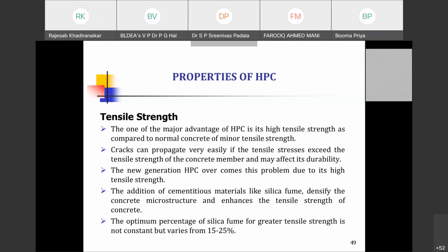The addition of supplementary cementitious materials, or SCMs, like silica fume or fly ash, densifies the concrete microstructure and enhances the tensile strength of the concrete. The optimum percentage of silica fume, as you have seen earlier, is around 15%. They define 15 to 20, but 15 is the best.